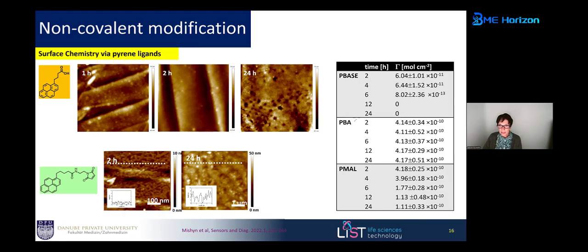Then if you compare this to the acid, yes, here we keep the acid over time, so you cannot hydrolyze it. But what you see from the AFM is that over time, instead of covering the whole surface, you will probably get more of a 3D structure on it because the pyrene units stack over it. But there will be some holes left, and these holes would mean you will have direct access to the graphene interface, which is not ideal when you want to work with media like blood or plant juice, because you will have a lot of problems with non-specific absorption.